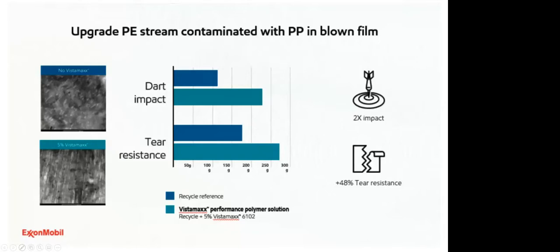The phase separation inhibits interfacial adhesion and decreases the mechanical properties of the melt blends. By adding 5% Vistamaxx 6102 polymer, the recycled output becomes a high-quality recycle. The Vistamaxx polymers act as a compatibilizer, improve the blend morphology, and reduce the surface energy.